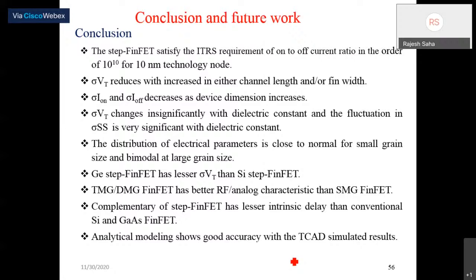Similarly, the on current and the off current also provide better performance as the dimension increases. Sigma VT changes insignificantly with dielectric constant, whereas the fluctuation in sigma SS is very significant with dielectric constant. And the distribution plot for various electrical parameters is close to normal for small grain size and becomes bimodal at larger grain size.